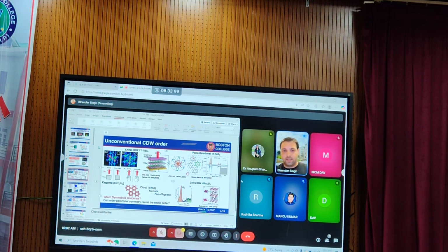So this is the crystal structure I have studied, these rare earth tritellurides. It consists of two building blocks. One is this RTe layer, which is completely insulating, so it's kind of boring. Another is this tellurium layer. This is the place where the charge order takes place. It's a quasi two-dimensional system, and we can easily exfoliate it and reduce the dimensionality of this system. It has px and py orbitals of tellurium, and bands near the Fermi surface mainly come from these px and py orbitals.